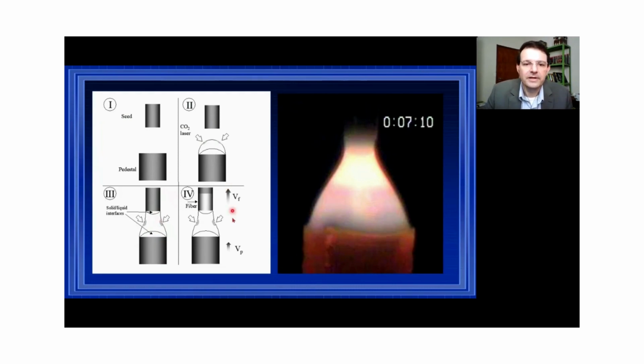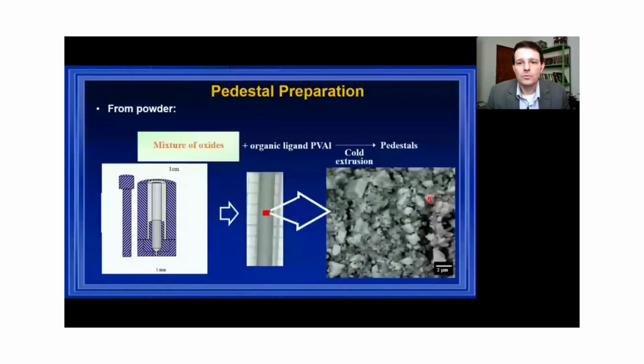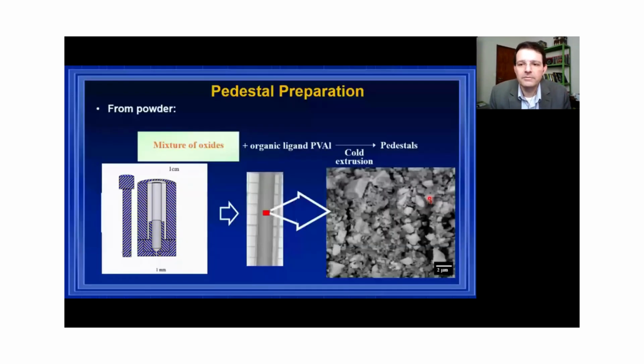Then you can start the pulling. Here is the photograph. This is about 1 millimeter in size. So the drawback is small samples, but it's not really a drawback, because we would like to have miniaturized devices. So one thing compensates the other, okay? What we discovered is that you don't have to pre-react the compound that you would like to grow or melt, okay?